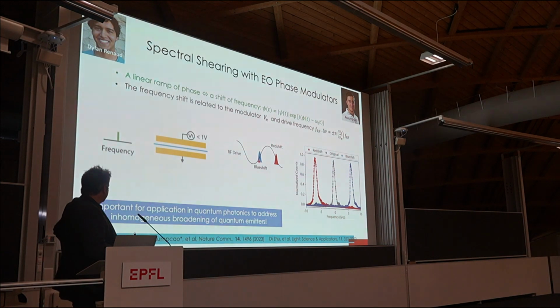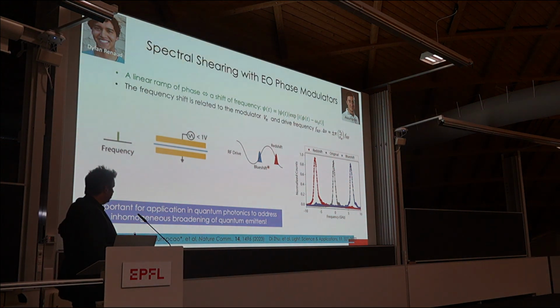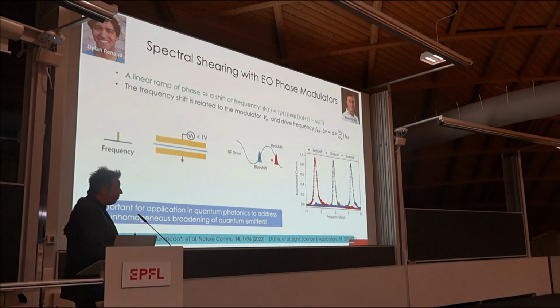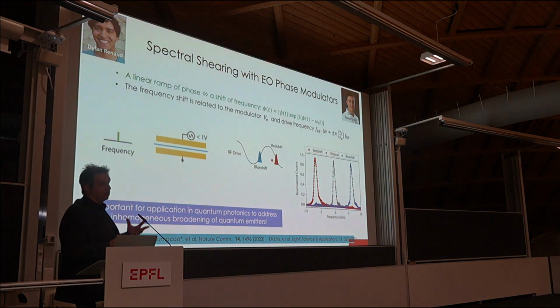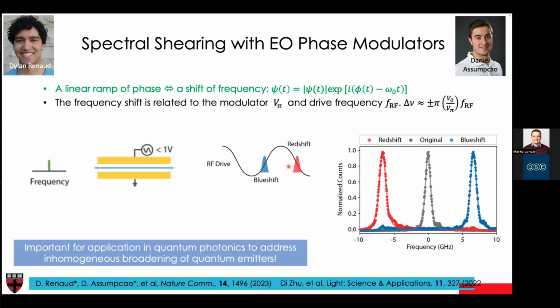So this works really well actually. It's very simple. The drawback is that you need short pulses, because your optical pulse needs to be shorter than the rising or falling edge of your sound wave. And our pulses, as I told you, in silicon devices are very long. So that's actually limiting efficiency. If you have a short pulse, this works beautifully. If this was a 50-femtosecond short pulse, you could shift this by hundreds of gigahertz, no problem. In fact, we can demonstrate that already.